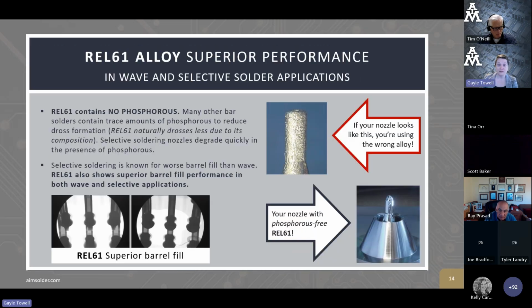And again, with selective and wave soldering, it works really, really well. We sometimes have people ask, does it contain phosphorus, which is used to reduce dross? It does not. Many bar solders contain trace amounts of phosphorus to reduce dross, but REL61, possibly due to that bismuth content, dross is less. Selective soldering nozzles degrade really fast with phosphorus. There's a picture example here, but REL61 doesn't have that in it, so you don't end up with that issue. Selective soldering is also known for getting worse barrel fill than wave soldering, but REL61 seems to have really great barrel fill with wave and selective applications. So again, that might be the bismuth content contributing to its ability to flow well when it's in molten form.